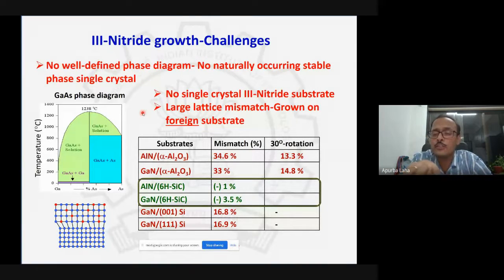I won't go into the details about the growth, but given the requirements for a layer grown on a single crystal substrate, the available substrates are sapphire, silicon carbide, and silicon. Fine, we have available single crystal substrates, but let's look at the lattice constants. When you are building these systems, like here on the left side, there is a single crystal substrate. On top, you have a limitation: you cannot grow a layer with a lattice constant, the distance between two atoms in this case, far different from the substrate. That makes it very challenging.